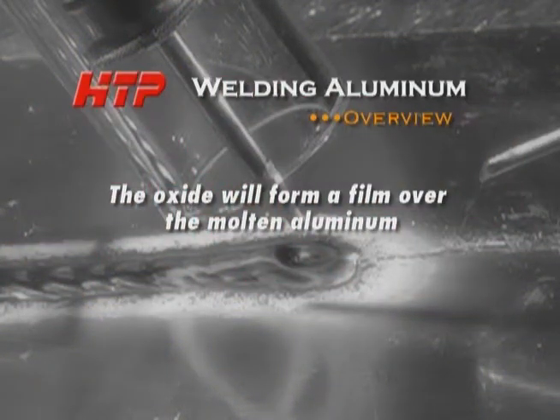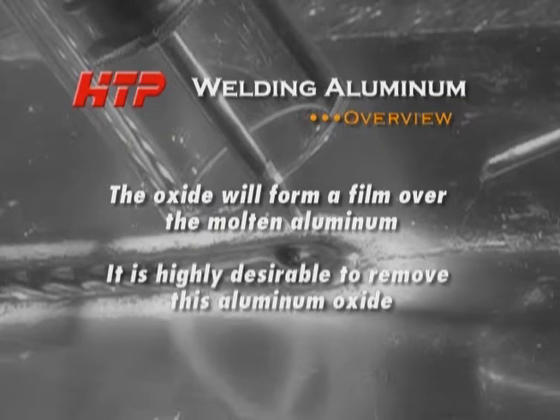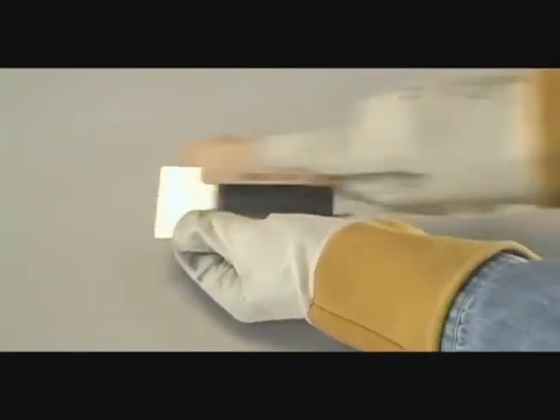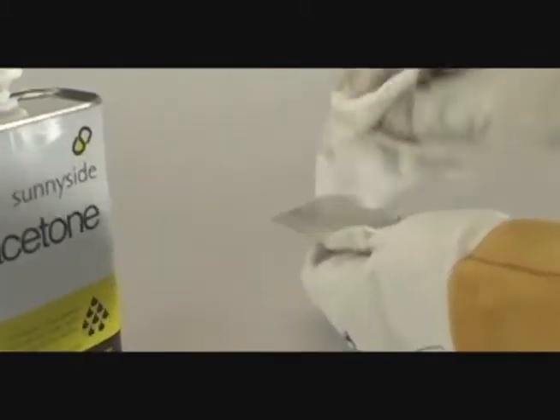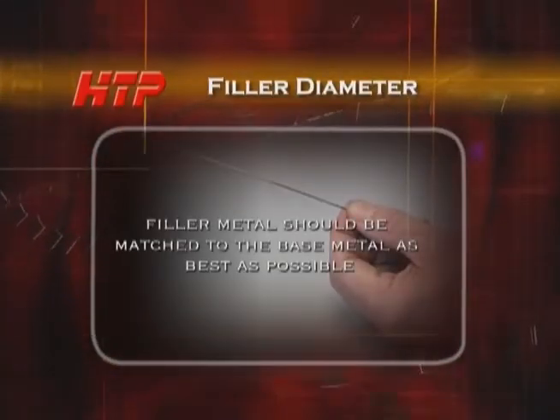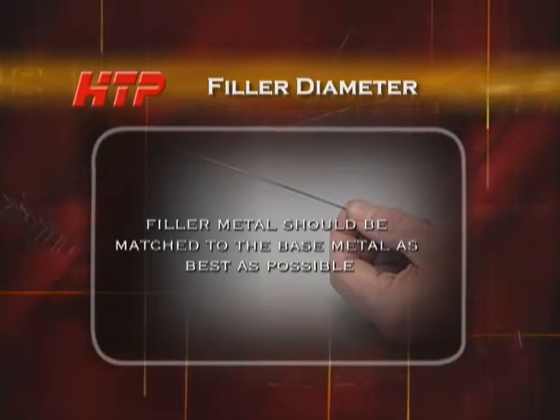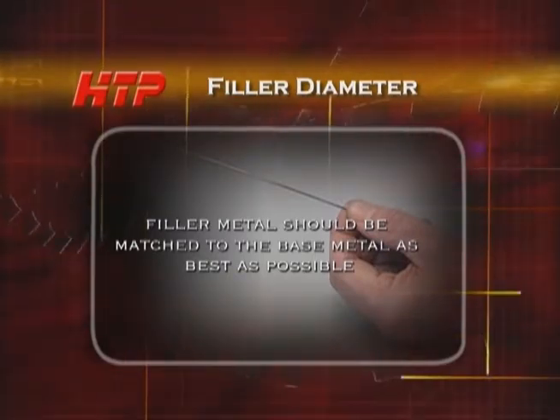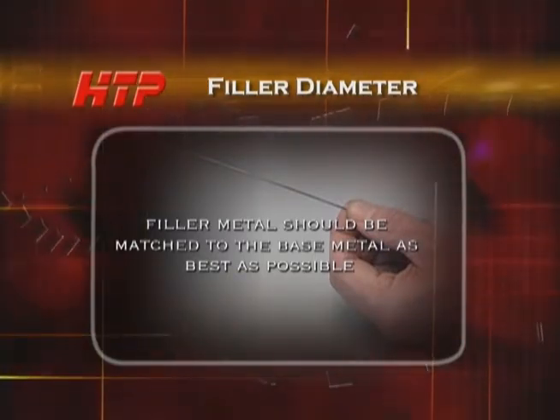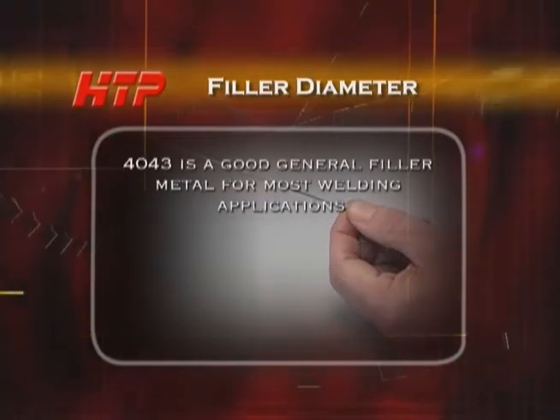The oxide will form a film over the molten aluminum, so it is highly desirable to remove the aluminum oxide. The oxide can be removed with a stainless steel wire brush or a Scotch-Brite pad and then wiped down with acetone or lacquer thinner. When welding aluminum, the filler metal should be matched to the base metal as best as possible. However, in a repair application, many times we don't have the luxury of knowing what alloy we're actually working with. Generally speaking,